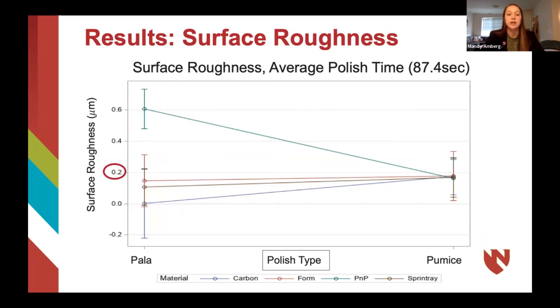a statistically significant increase in surface roughness in the conventional material with polish group compared to all other treatments. On the right, you can see that there were similar surface roughness results for all materials when polished with pumice. The red circle on the left depicts the clinically acceptable surface roughness threshold of 0.2 micrometers. As you can see, all sample groups except the conventional polish group were below this threshold, thus reached the optimal level of polishability.